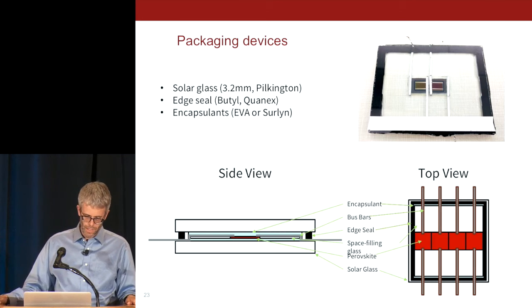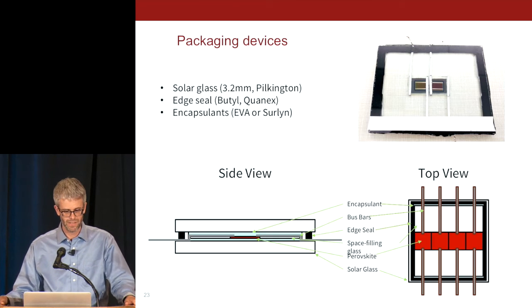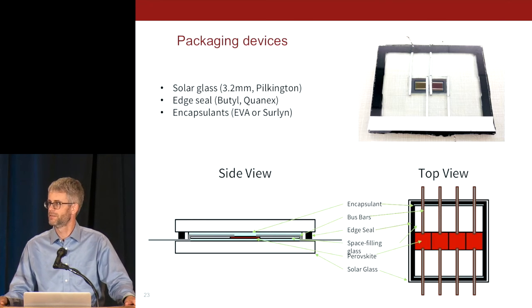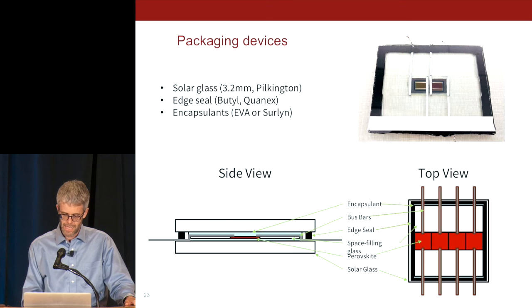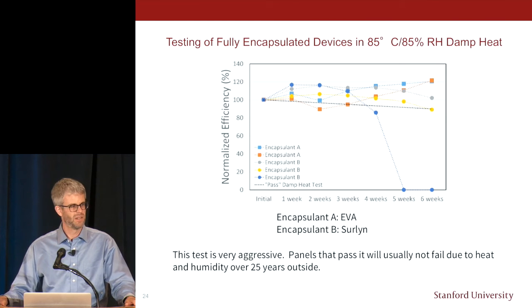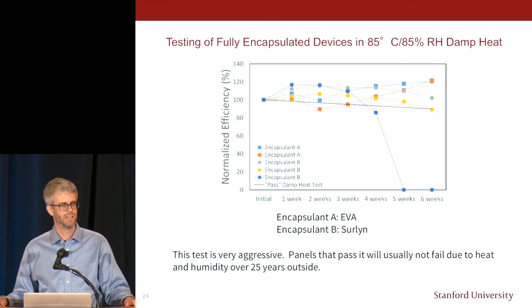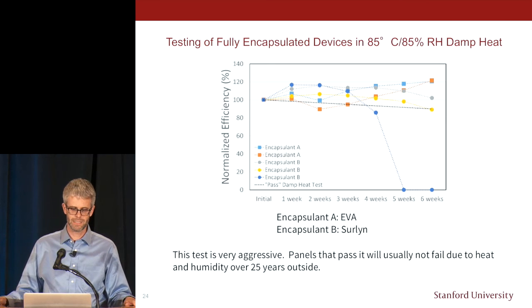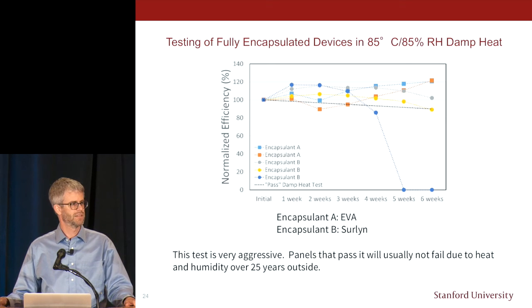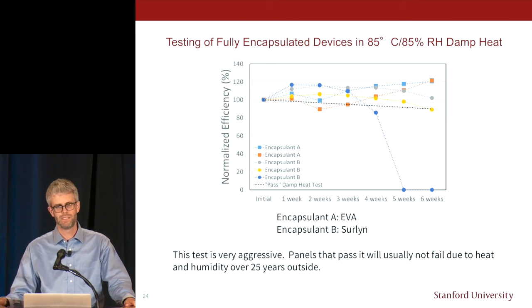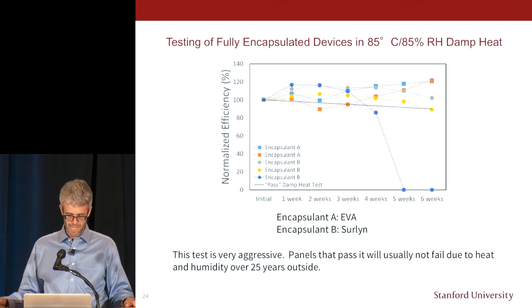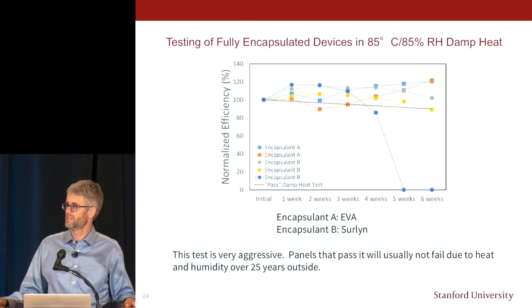And we didn't even try to invent anything here. We just use industry standard materials. And then we went out to pass the industry standard tests, the so-called IEC tests. One of them is 1,000 hours at 85 degrees C, 85% humidity. And two of our three packages we passed on the first run.